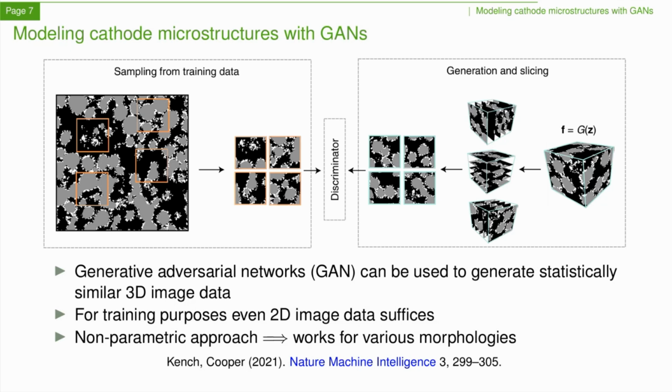And how do you calibrate, or how do you train the weights of these networks? Basically, you simulate measurements. You generate a virtual 3D image, then take virtual cross sections from that, so you get to these blue bounded patches, so that you have virtually simulated measurements. On the left-hand side you have cutouts of measurements, and these are passed to a neural network called the discriminator, and its sole task is to distinguish between these 2 types of images. But the generator, the neural network denoted by G, gets feedback of the discriminator's decision, and it tries to get better to fool this discriminator.